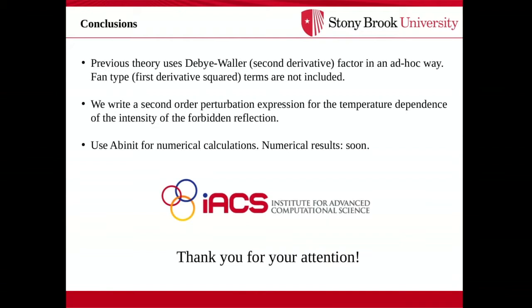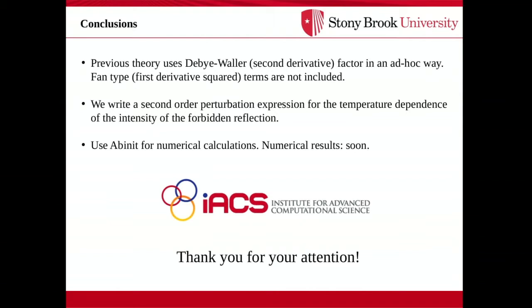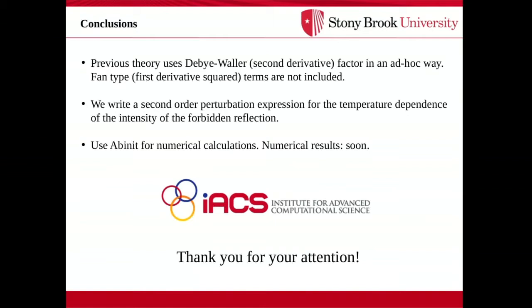Question: What would the cost of the calculation be compared to just calculating the energy? In Abinit, calculating just the energies takes maybe 10 minutes. A phonon calculation for a material with two atoms in a unit cell, using a Q-grid of 18×18×18 and two nodes with 16 processors per node here at IACS, took about 20 hours. Some people in Belgium do 100×100×100 grids, so they take a lot of time.